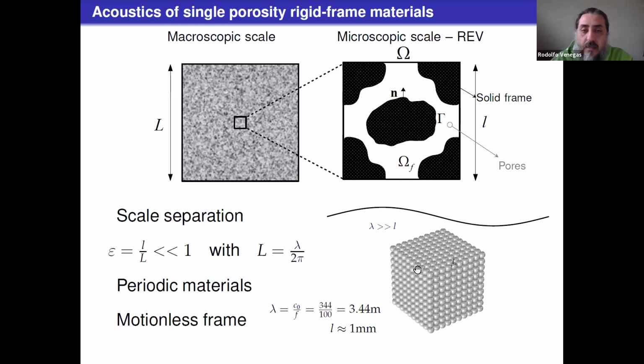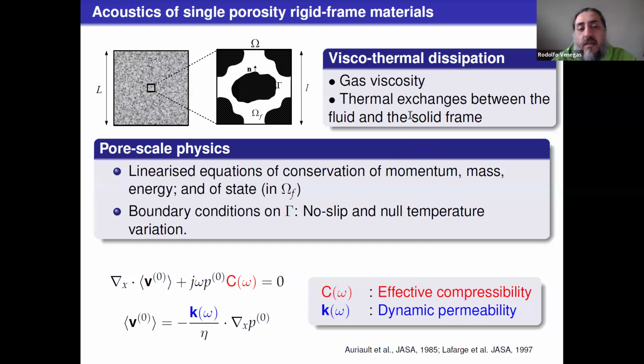So in terms of physics, we start from the linearized equations of conservation of momentum, mass, energy, and the equation of state, with boundary conditions of no slip and null temperature variation on this Gamma, on the walls of, for example, this grain. After applying homogenization, we get this macroscopic description, which is composed of the macroscopic equation of conservation of mass and this fluid flow constitutive law, which is the dynamic Darcy's law. In terms of dissipation, we have two main mechanisms responsible for the dissipation of sound energy, and one of them is gas viscosity and thermal exchanges.